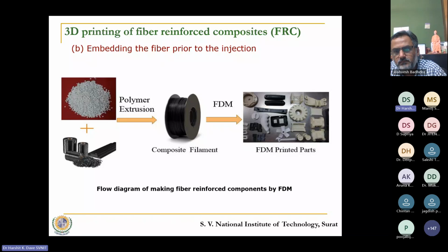The second process which we see in the literature is by embedding the fiber prior to the injection. So what it means necessarily is that we create a filament wherein fibers are mixed into the filament. So we need to go for a polymer extrusion process. We select a proportion of chopped fibers, say 1%, 5%, 10%, 20%, whatever it may be. That percentage of fiber is mixed with the polymer granules, and then they undergo the extrusion process. I'll not go into the extrusion process right now because I'm going to discuss that in detail in the other process. So because of that polymer extrusion, we create a composite filament, and these composite filaments are widely used for creating parts.